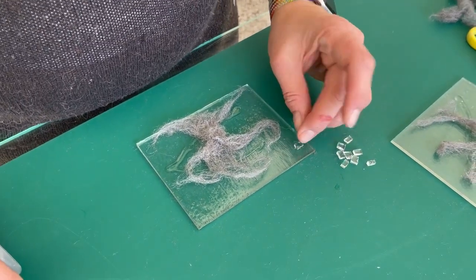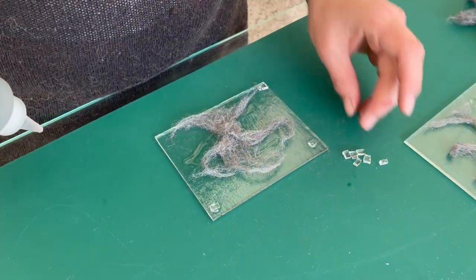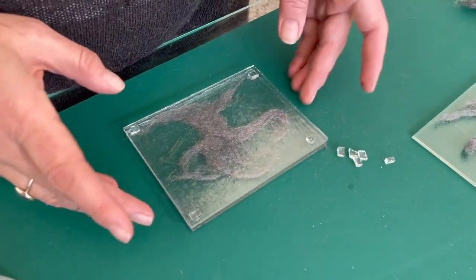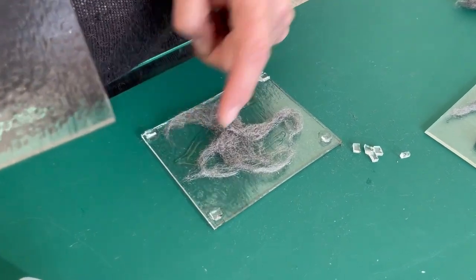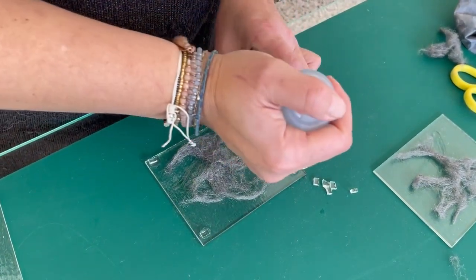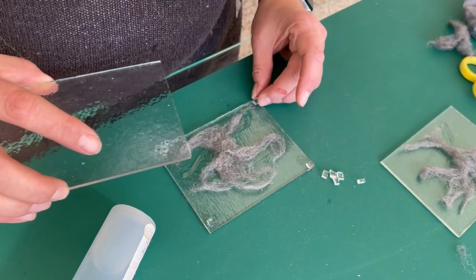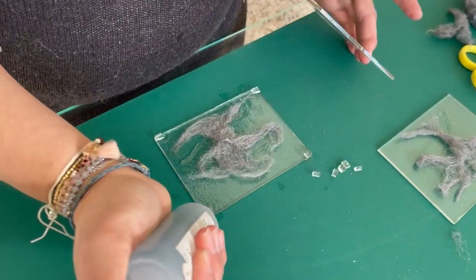You need some small pieces of glass to put in the corners. We'll then do a two-hour bubble squeeze, which holds the glass up at the edge, hopefully giving time for all the bubbles to move out before the glass closes in on itself. This is also a great project to do with float glass, because float glass is stiffer and it just works really well.